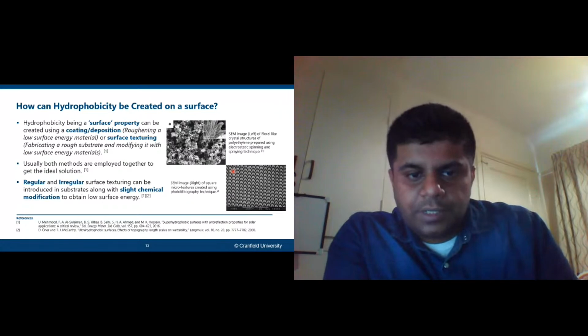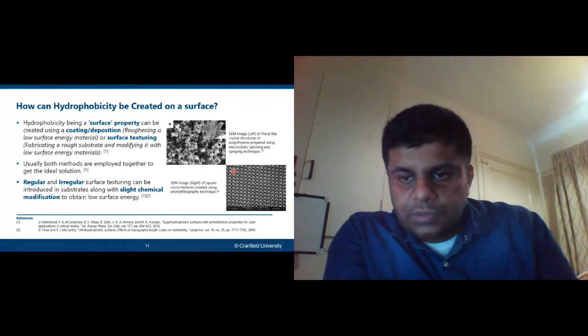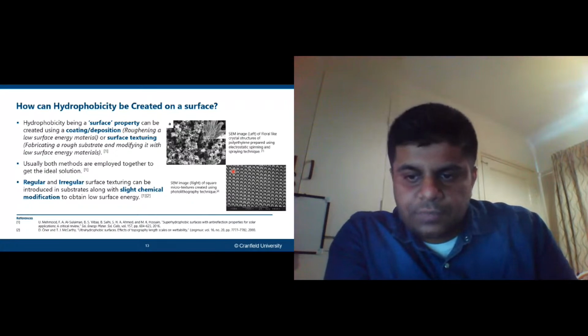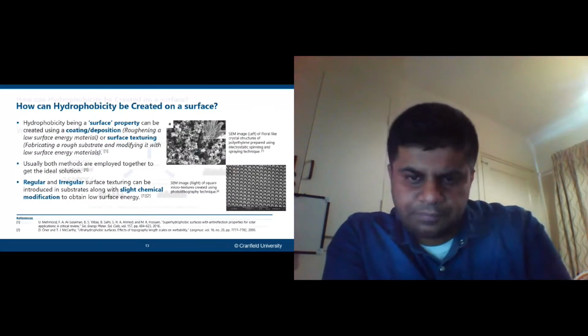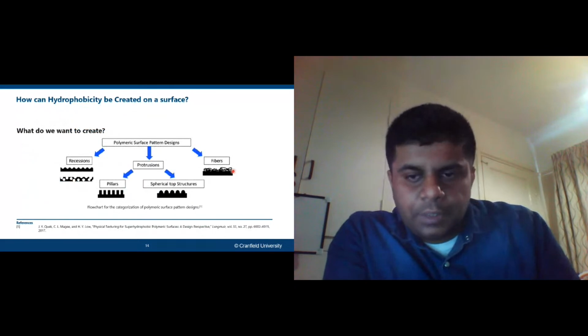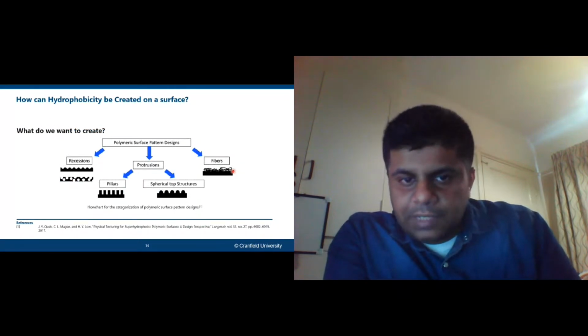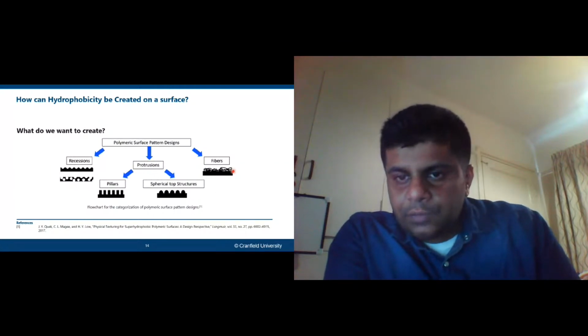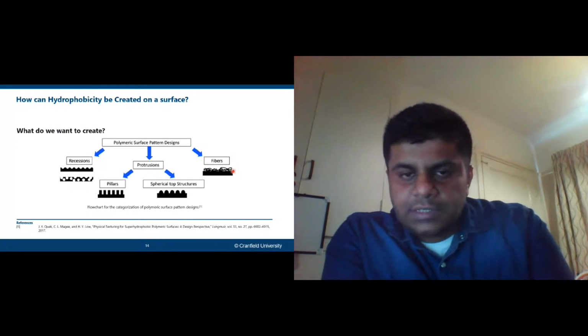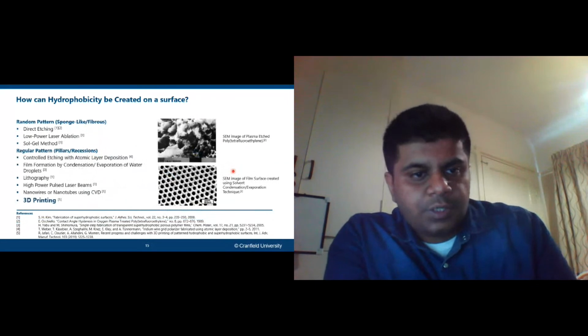So you can have regular and irregular surface texturing, and that can be achieved with slight chemical modification as well as mechanical means to obtain low surface energy, so that your droplet actually rests on the surface and does not fully immerse into it. So at the end of the day, it all comes down to what you want to create. If you want to create regular patterns like recessions, pillars, spherical top structures, you go for a more ordered technique. And if you want to create fibrous structures or irregular patterns, you go for chemical etching and stuff like that. So these are some of the techniques that you can use.